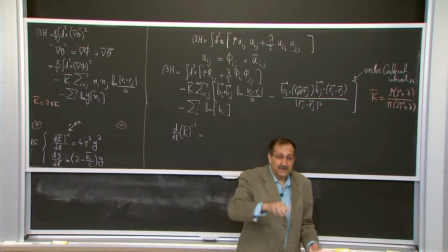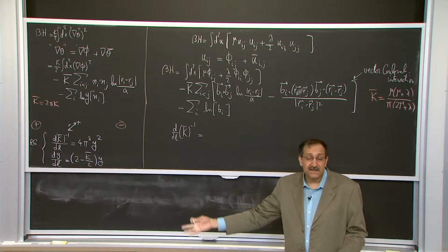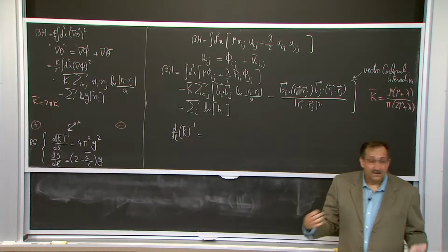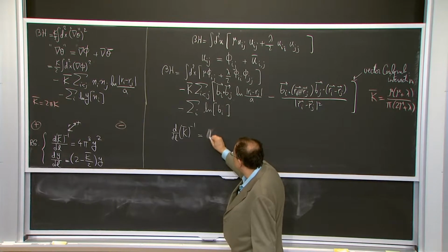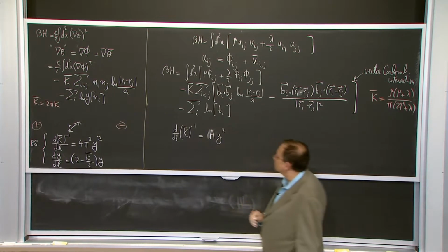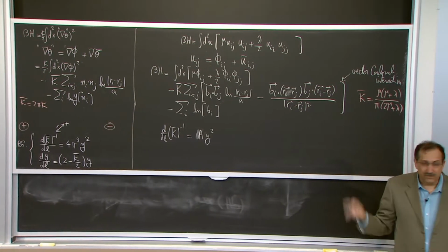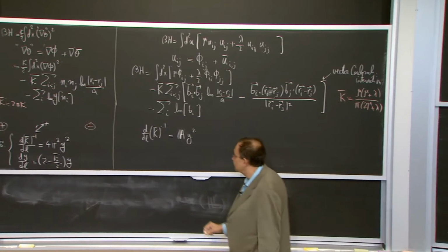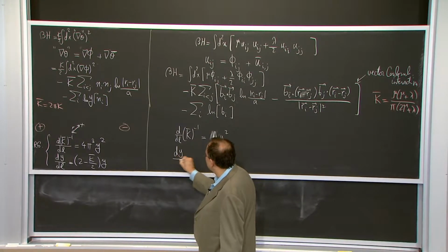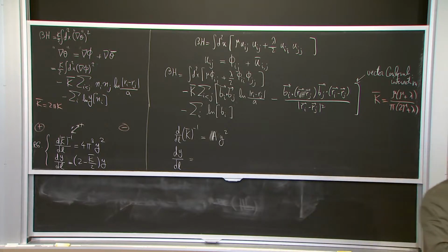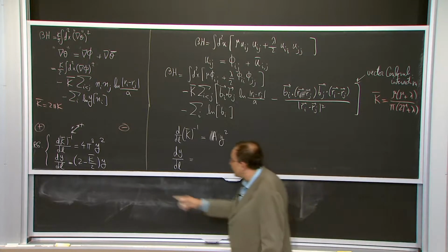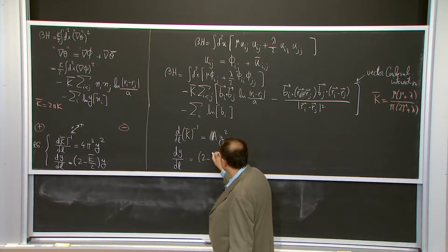That is, there will be charges that appear, all the mathematics is clearly similar, and there will be a reduction, which you can think of as an increase in temperature, proportional to y squared. I don't know what the constant of proportionality is. And dy by dl, so essentially I focus on the simplest type of dislocations that I could have, of unit spacing, has exactly the same form, 2 minus k bar over 2, times y.